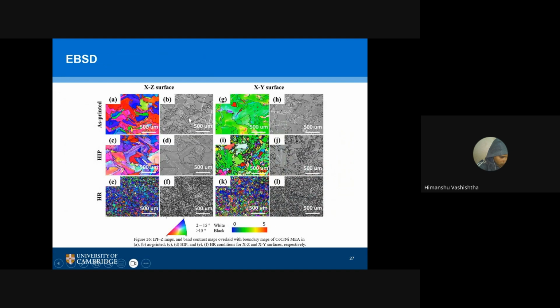The answer lies in these white lines, right? White lines mean a high amount of low angle grain boundaries, or technically a high amount of dislocations. What are these dislocations doing? If you apply any load, let's say you're measuring the hardness, applying a load and measuring the hardness - if a lot of defects or dislocations were there, this will hinder the movement of your atomic structure, the elements, the grains. It will stop the movement of your atoms, and that's how, if your atoms are not moving, that means it's high hardness. So it's playing a role.